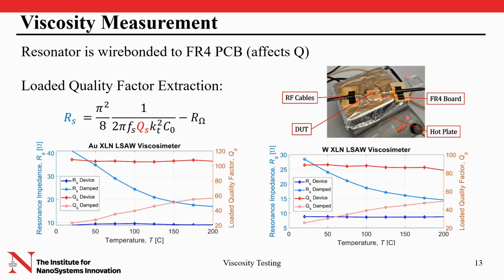For the testing, we simply wire bonded our resonators, both the gold and the tungsten one, to an FR4 PCB. Unfortunately, very long wire bonds were necessary for this testing, and they ultimately impacted the quality factor of our resonator, but we were still able to measure it. Two sets of measurements were carried out. One for the temperature only, because we need to characterize the temperature response by itself. This was done via direct RF probing. We wanted to double check once we loaded the resonator with the wire bonds, and then we applied the oil and heated it up.